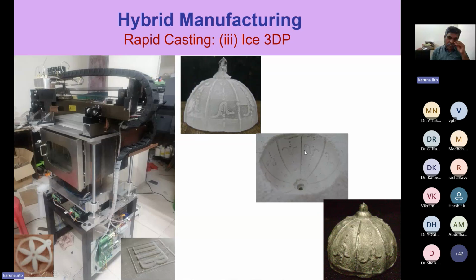So we adapted a very interesting method called sublimation. You know what is sublimation? From solid state, you can go directly into a gaseous state. From ice, it will become vapor or steam. So that's what we did. This is also known as freeze casting, because after pouring the slurry, we put the whole thing inside a refrigerator and also apply vacuum on it. See, ultimately the region, whether it is sublimation region or melting region, depends on the pressure and temperature you apply on it. We did that and we were able to get the mold very nicely reproduced. Then we obtained the metal casting from that. So this was built by a PhD student single-handedly. Today he is a faculty in BITS Pilani.